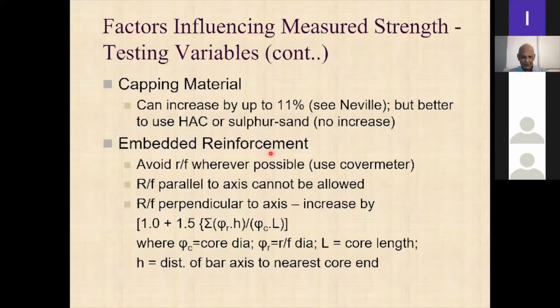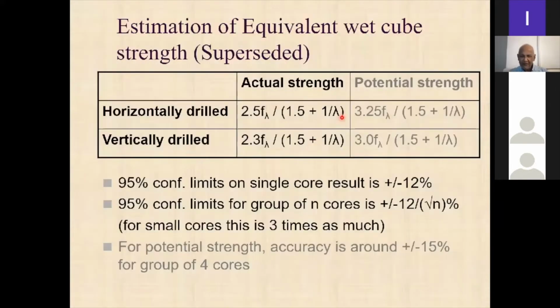Okay, and I'm going to skip this also. And here, this lambda is the length upon diameter ratio, right? And so for a horizontally drilled core, this will give you the equivalent cube strength. And for a vertically drilled core, this will give you the equivalent cube strength, right? So this is the actual strength of the core, which has an L upon D ratio of this. Lambda is length divided by diameter, right? And the actual strength will be obtained by using this formula for vertically drilled cores and this formula for horizontally drilled cores, right?